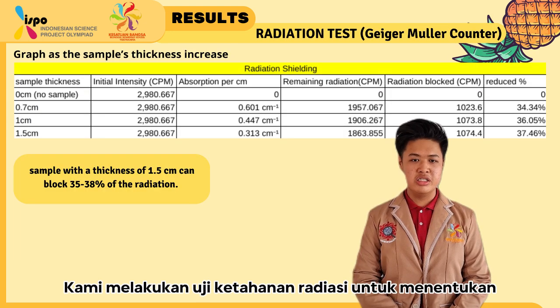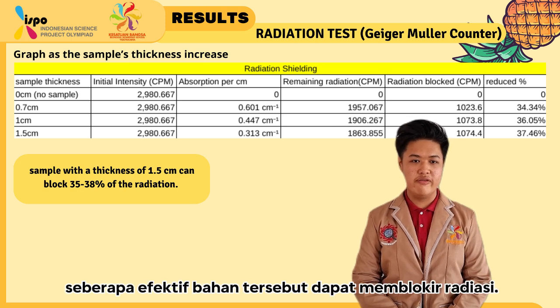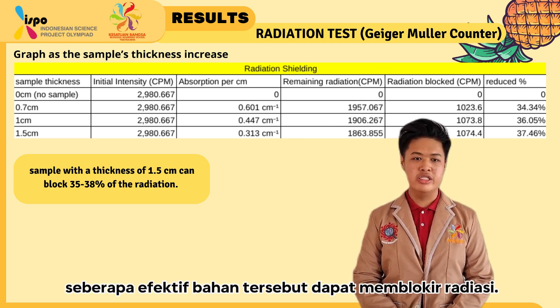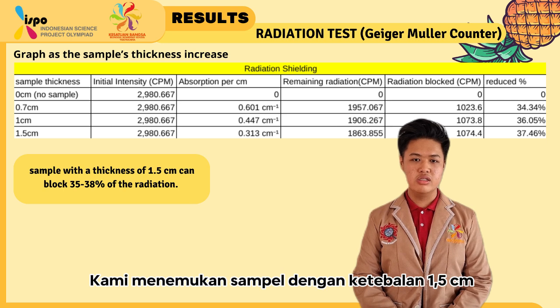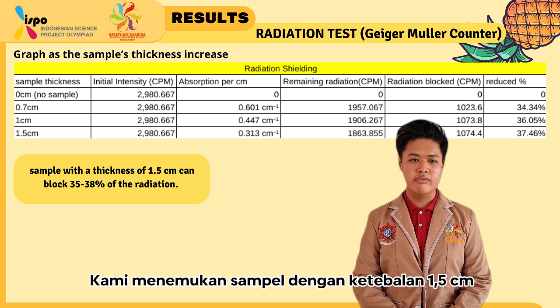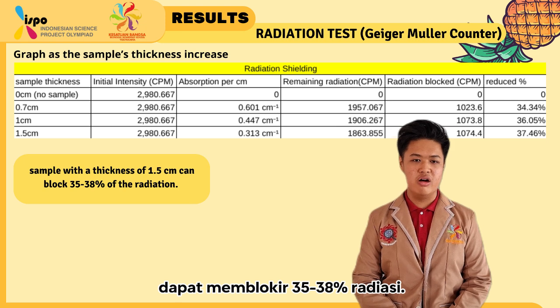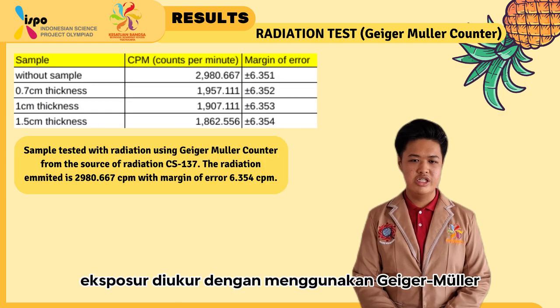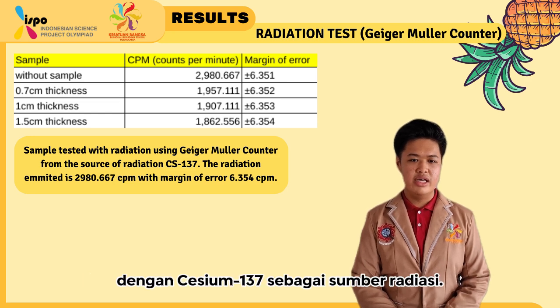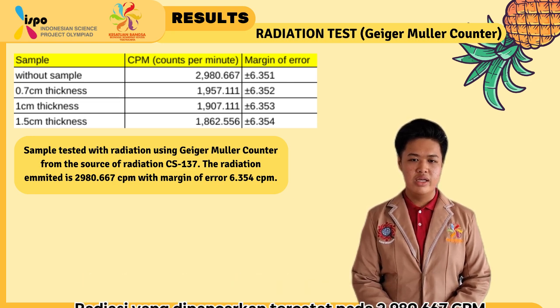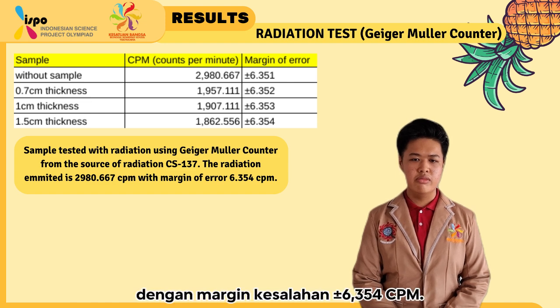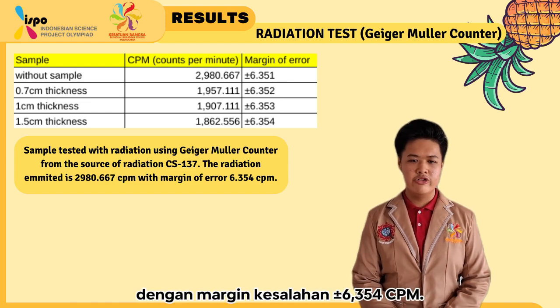We conducted a radiation resistance test to determine how effectively the material can block radiation. We found a sample with a thickness of 1.5 centimeters can block 35 to 38% of the radiation. Exposure was measured using a Geiger-Müller counter with cesium-137 as a radiation source. The emitted radiation was recorded at 2,980.667 CPM with a margin of error of 6.354 CPM.